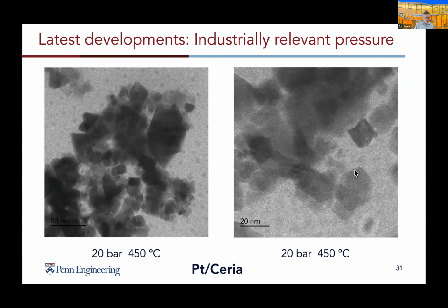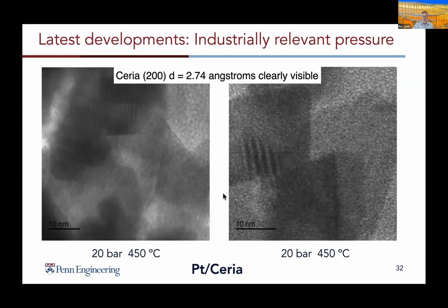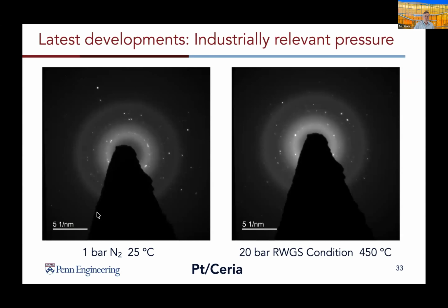And with this, in the latest work from December of this past year, you can see very nice images at 20 bar and 450 degrees C for platinum supported on ceria. And if you look deeper, there's clear images of 2.74 angstroms being resolved in the ceria 200, again at 20 bar and 450 degrees C. We know we have 20 bar because if we look in the electron energy loss spectra, it's just one big hump of scatter. But the imaging here using the zero loss filtering allows us to recover atomic levels of resolution.